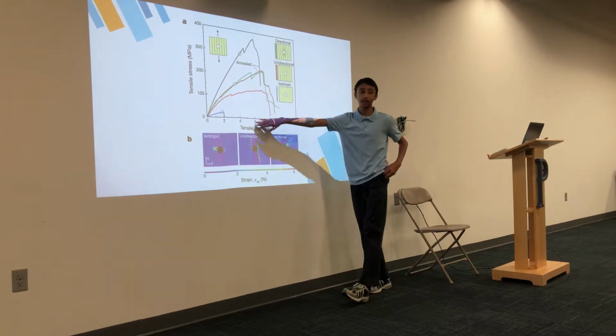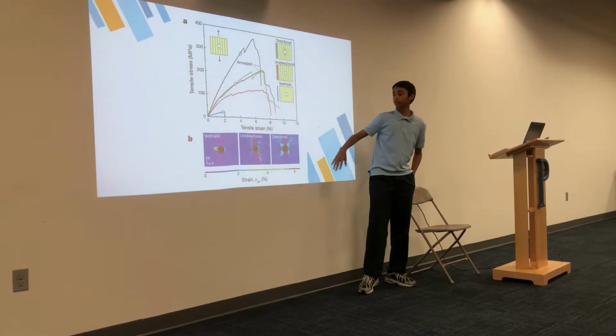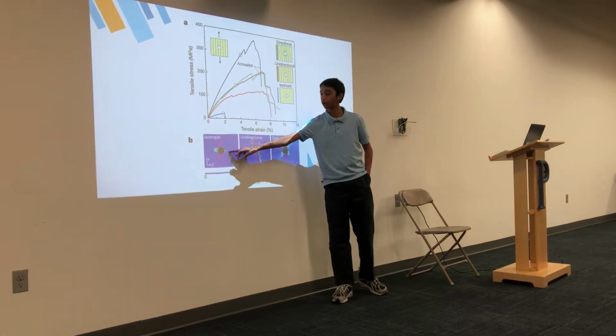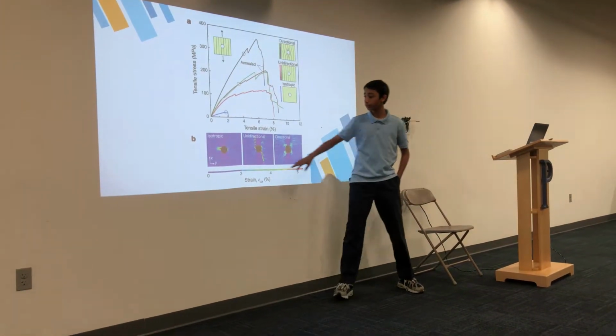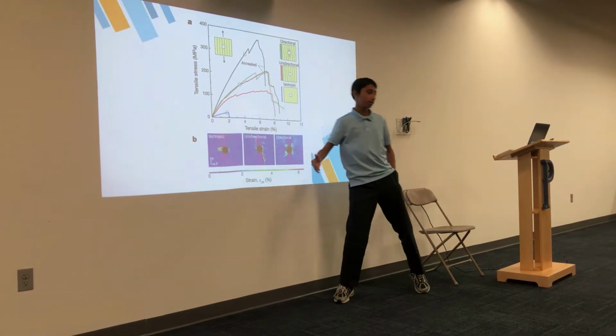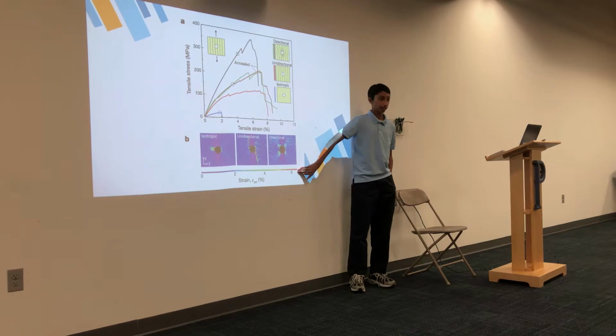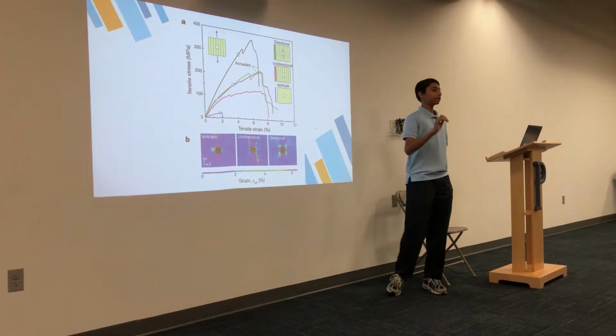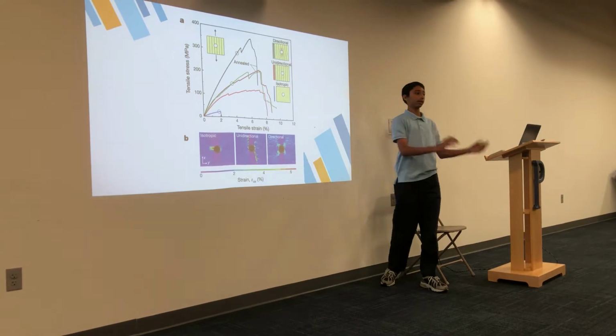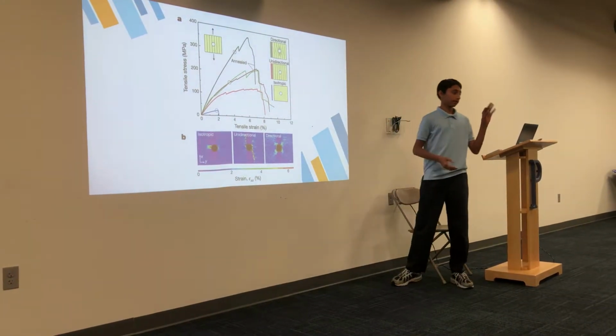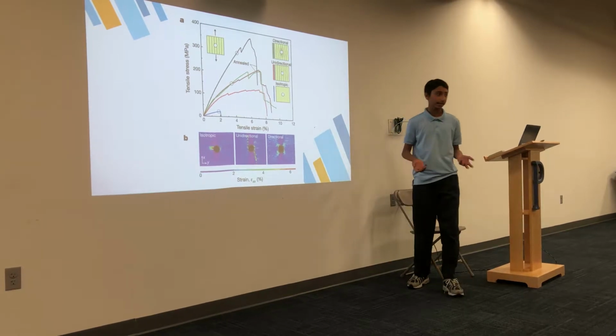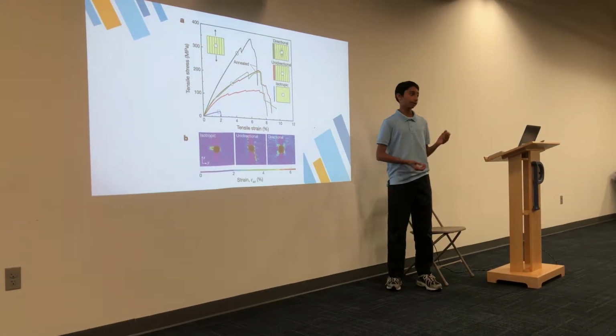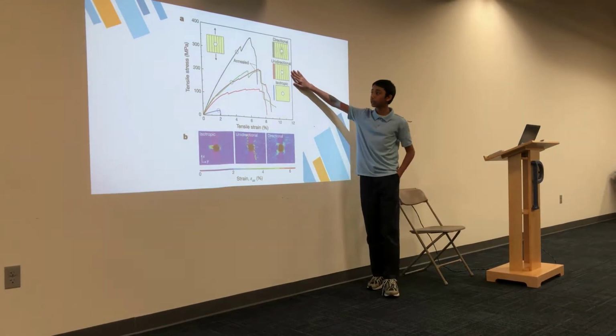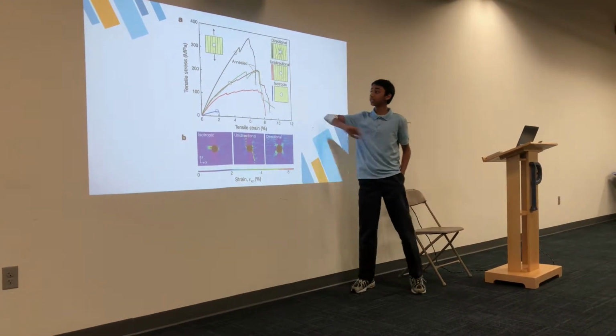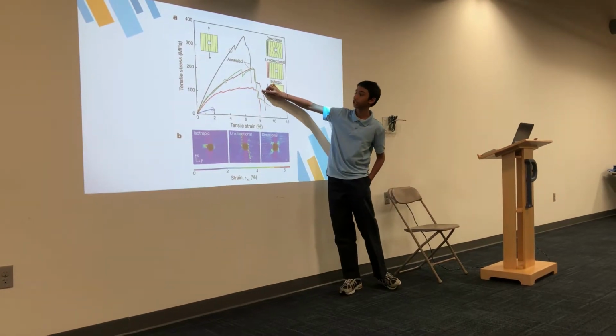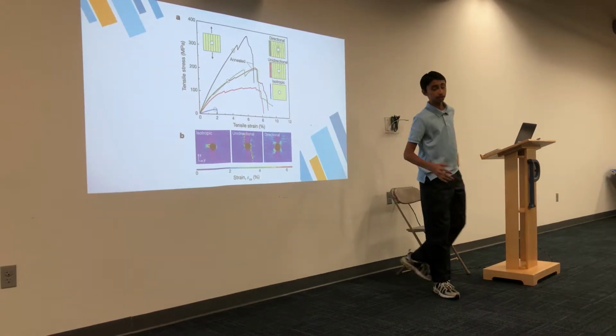So we look at the isotropic, it did horrendously, because when you pull it apart, if we look at this graph of where the strain was being distributed, there's a huge bulge over here, which means that's what took the majority of the strain. It's not being distributed evenly at all. It's just being lumped to a side, and obviously because that amount of material is not meant to take that much strain, it's going to catastrophically fail a lot earlier. If we look at the unidirectional material, this does much better. Specifically the annealed, which is this darker brown line, is a lot stronger.